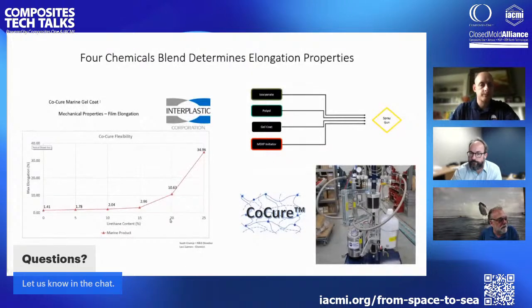So if we say CoCure 20, that's 20% urethane content. That means 20% of the constituents are the A and B chemical. If you go to CoCure 0, that's gel coat today with about a 1.4% elongation. Nothing much happens till you get to about 15% urethane, and then it starts really kicking in. Between 10 and 15, you'll notice you get a doubling of elongation. And this 15% is a real sweet spot.